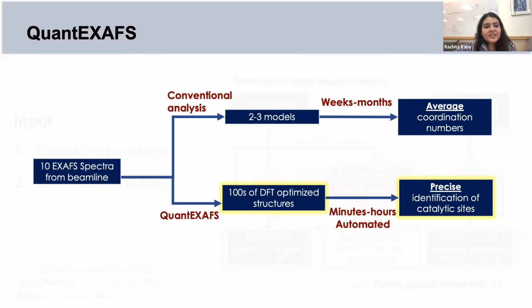We're not really fitting any coordination there. So there is barely any. So as long as it's a homogeneous site, it really fits well to the specific structure, provided you account for all the defects and all the adsorbates that could possibly be present in the system.